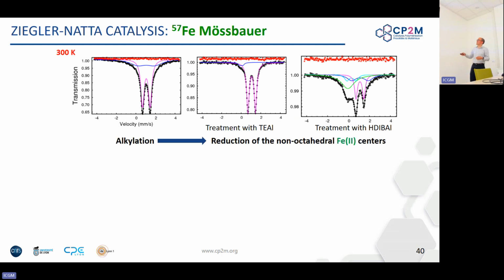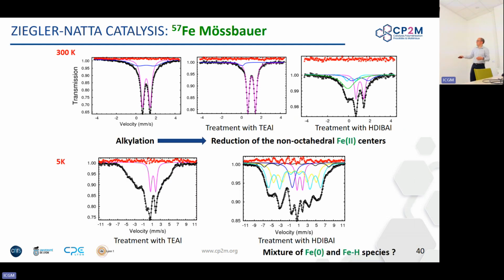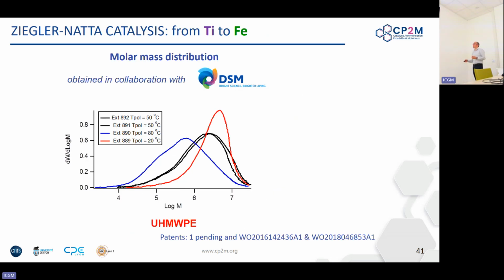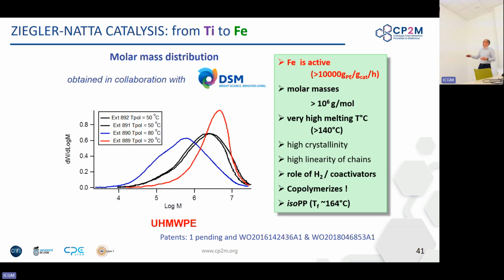Just a comment about the molar masses. We suspect that we are generating iron hydride species that are key for the polymerization. That explains why aluminum hydrides are a little bit better as activators compared to TEA. You can reach very high molar masses polymers with these. So these are more than 1 million grams per mole PEs. And you can even produce isotactic PP using this type of catalysis.